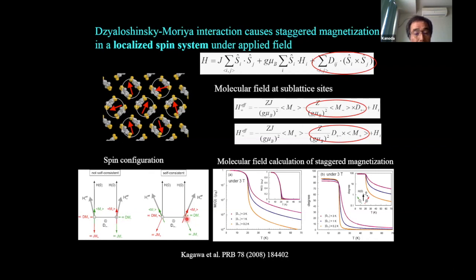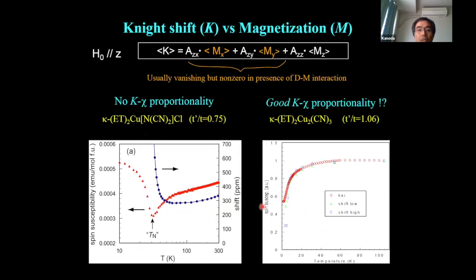So in the presence of Dzyaloshinskii-Moriya interactions, even in the paramagnetic state, the staggered component appears. And this is the mean field calculation: the staggered component is increasing as a function of temperature toward the Néel temperature. So this mx, my increases toward the Néel temperature. So this divergent increase of the Knight shift is this component.